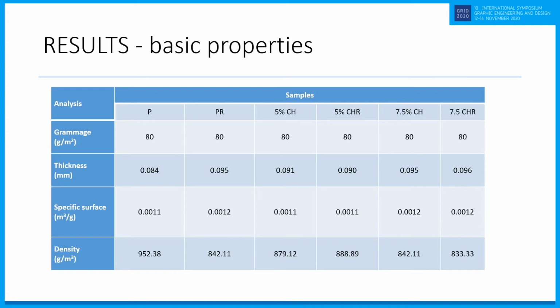As expected, you can see the thickness of the samples had mostly the same values. It's presented here in the table. Paper with only pulp, a combination of softwood and hardwood fibers with no additives, had the lowest thickness, and with the addition of the retention additive and fillers, the thickness of all other papers increased respectively. The changes were also detected in specific surface and density, where the sample with only pulp and no additives had the highest density compared to the other tested samples.